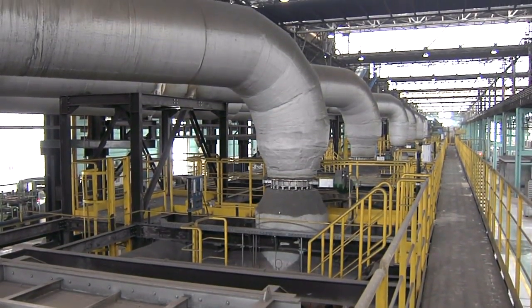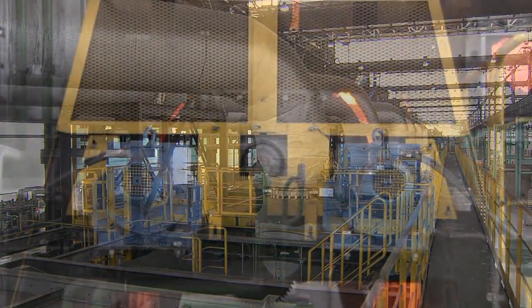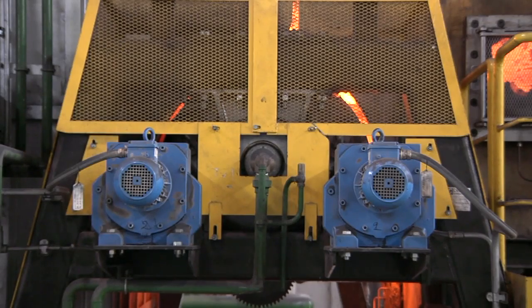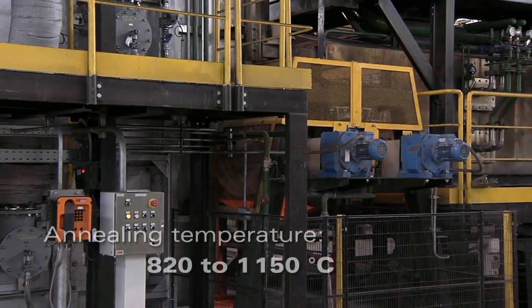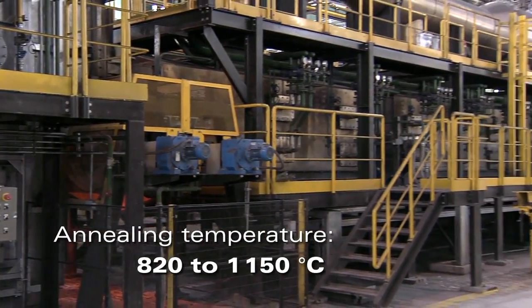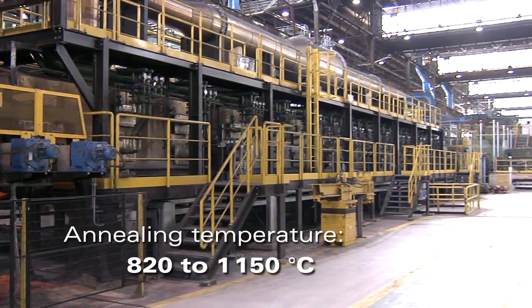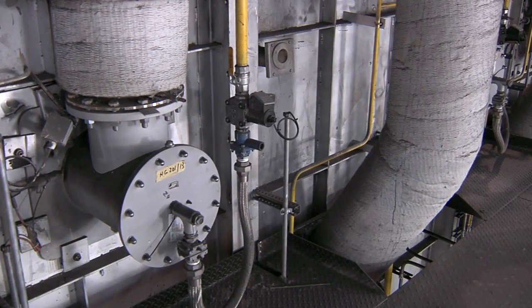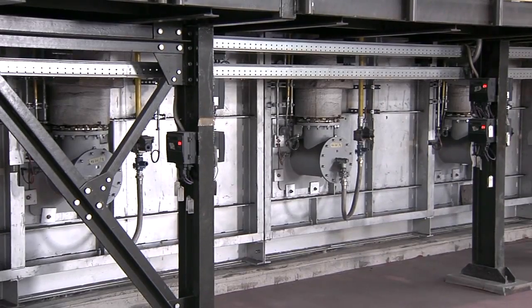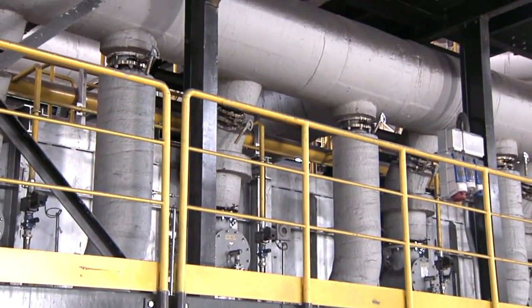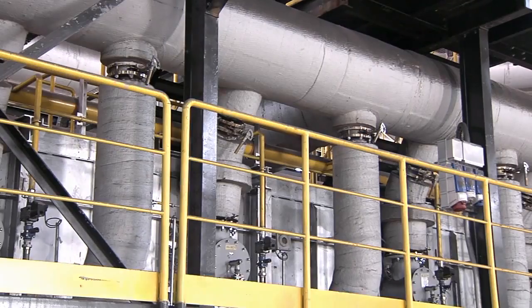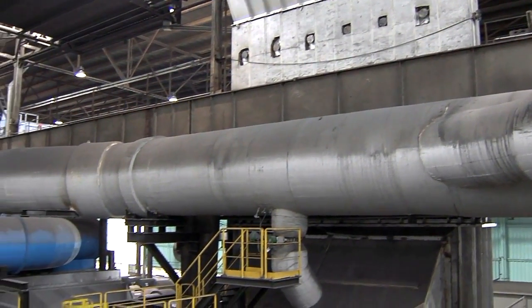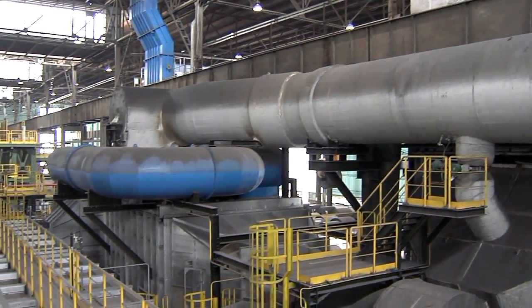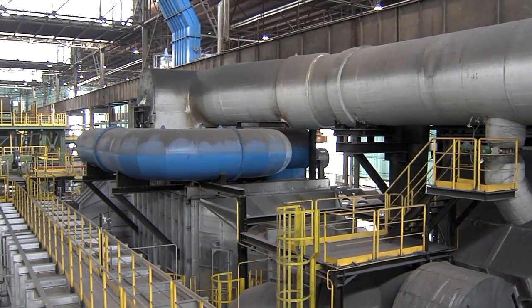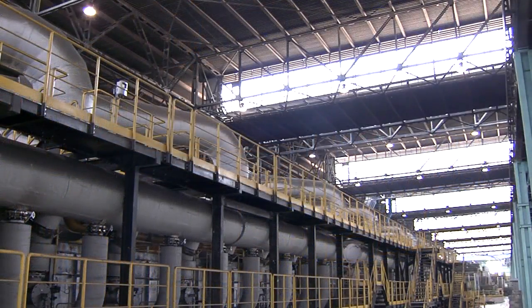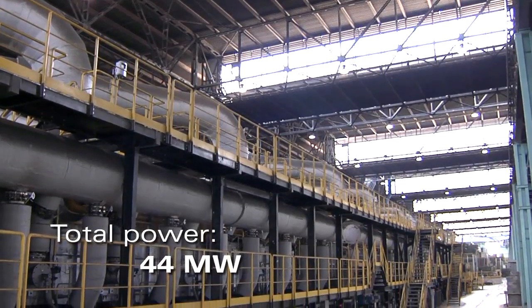In 7 zones, the strip is brought up to the annealing temperature stipulated by the process model. It ranges from 820 to 1150 degrees centigrade, depending on the steel grade, thickness, and strip width. Altogether, 108 natural gas burners ensure precise temperature control. To increase their thermal efficiency, the combustion air is preheated in a recuperator. The total power of the furnaces is 44 megawatts.